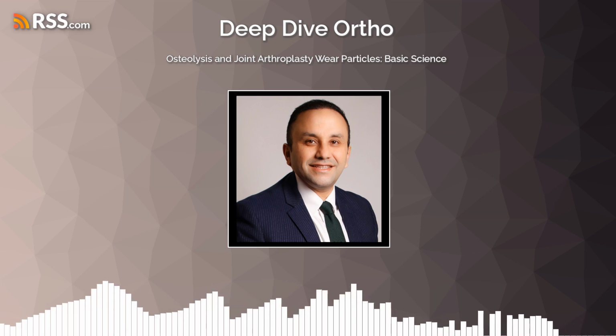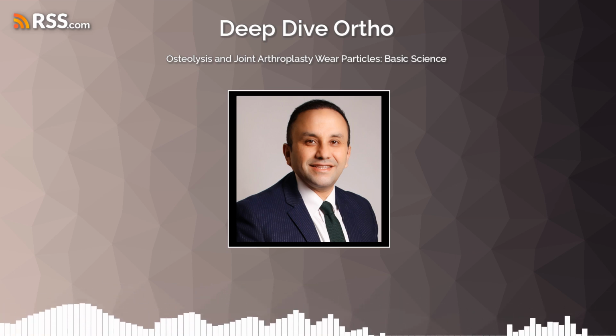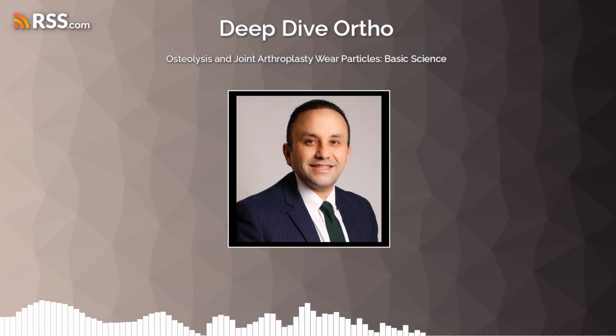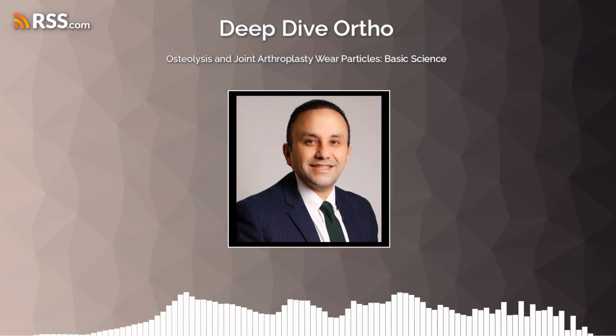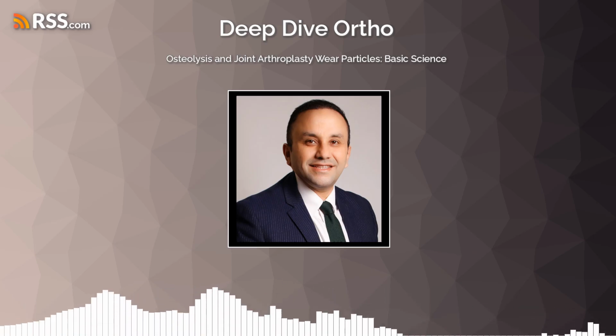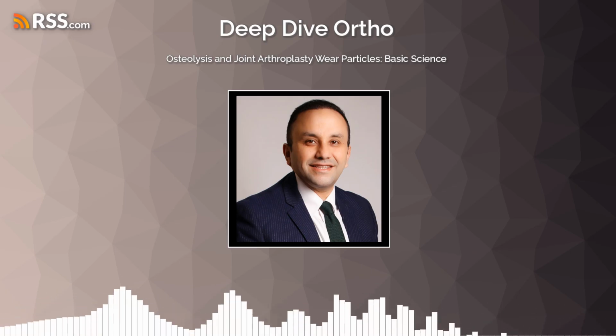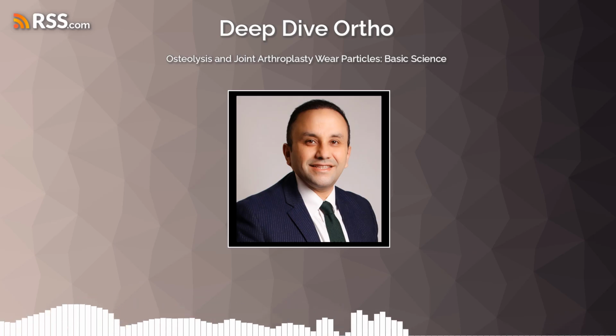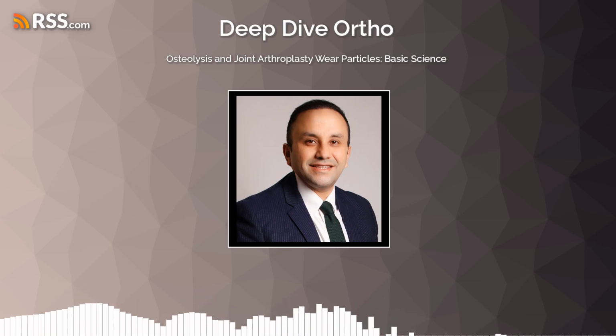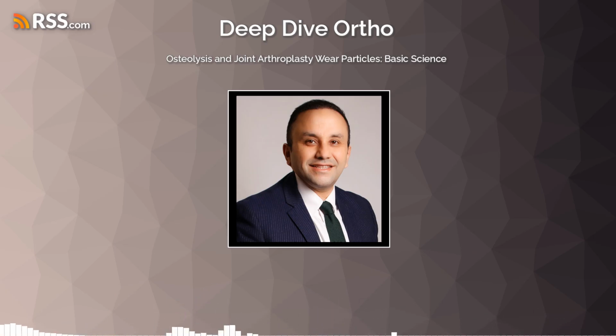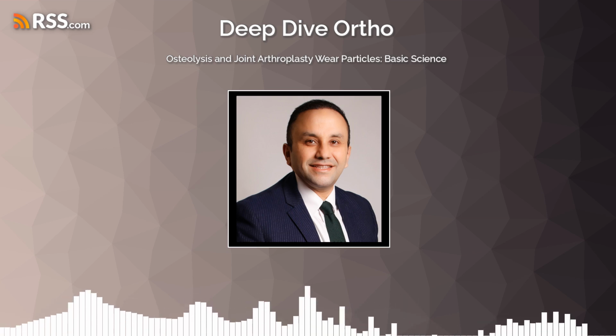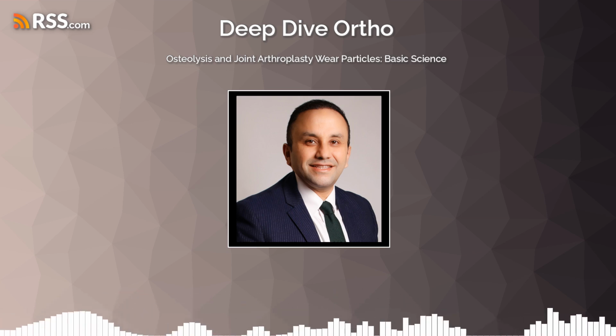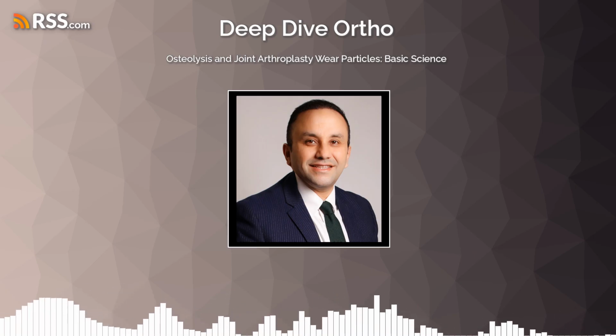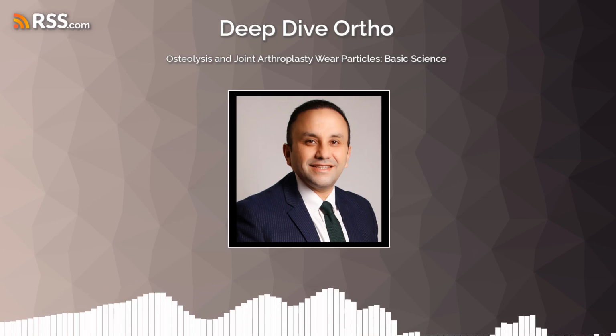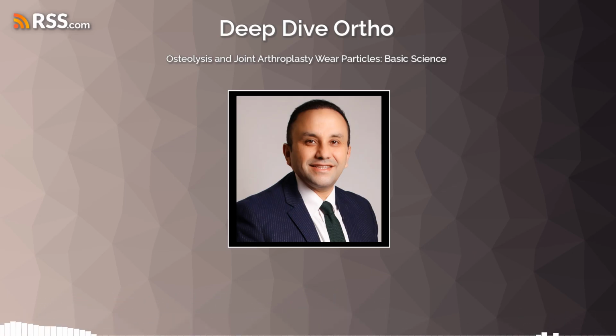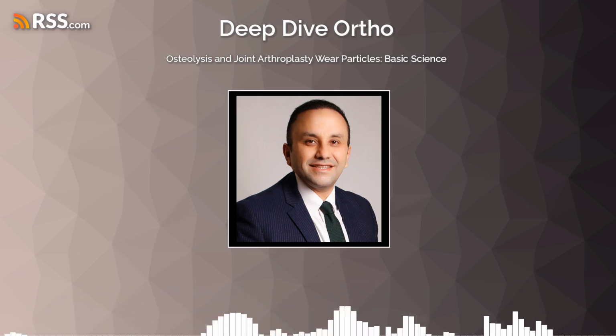How does that fit in? Well, 3D printing in orthopedic surgery is truly transformative. This technology allows for the creation of customized implants and even patient-specific surgical tools tailored precisely to an individual patient's anatomy. Personalized implants. Exactly. This can significantly improve surgical success rates by optimizing the fit and alignment of the implant within the bone. A perfectly fitting implant will experience less micromotion and more physiological load transfer. Which means less mechanical wear generation. Precisely. Furthermore, 3D printing allows for the creation of complex porous structures on the implant surface that actively encourage natural bone ingrowth, enhancing biological fixation and potentially making the implant more resilient to the stresses that generate wear. It's moving us towards truly personalized medicine in orthopedics. That sounds incredibly promising. It is.